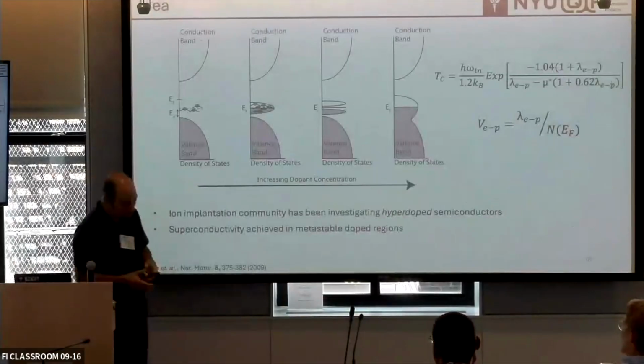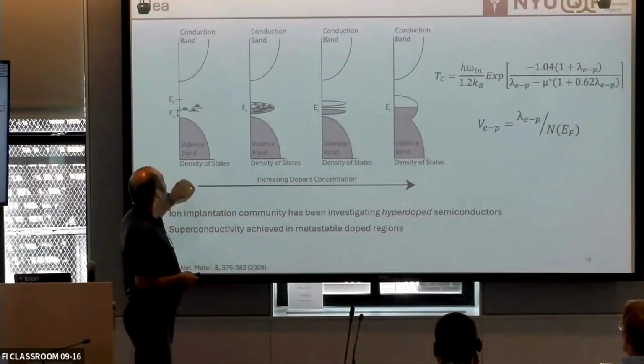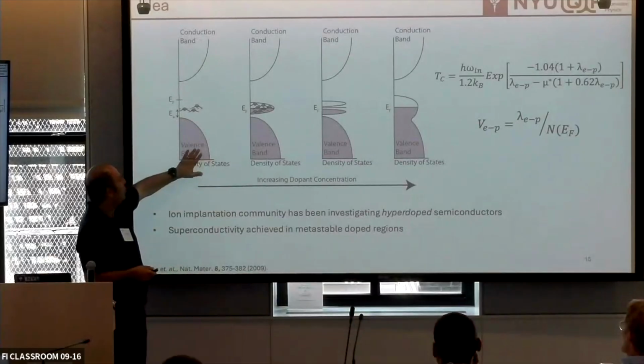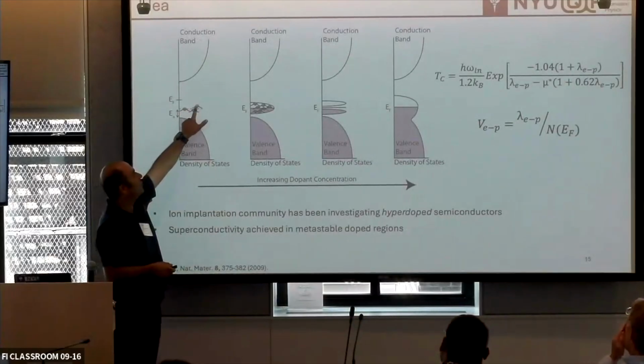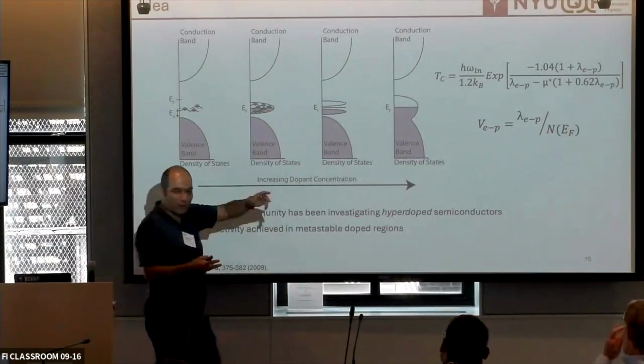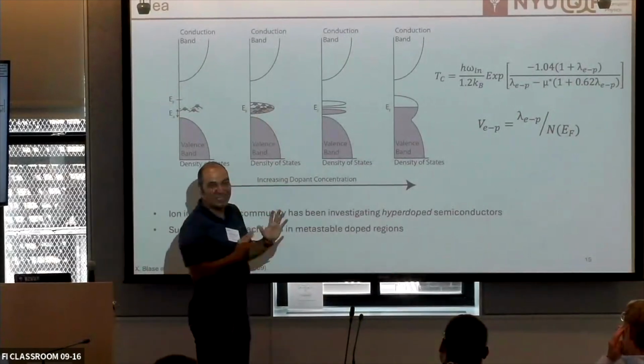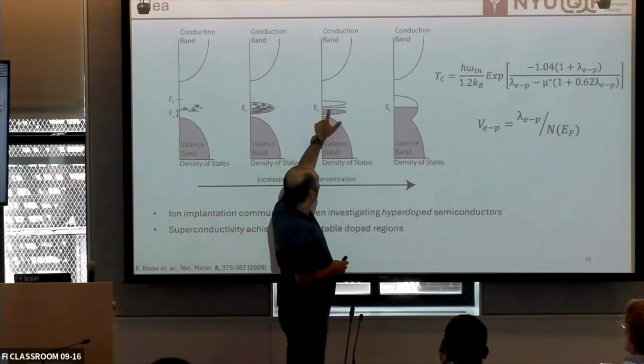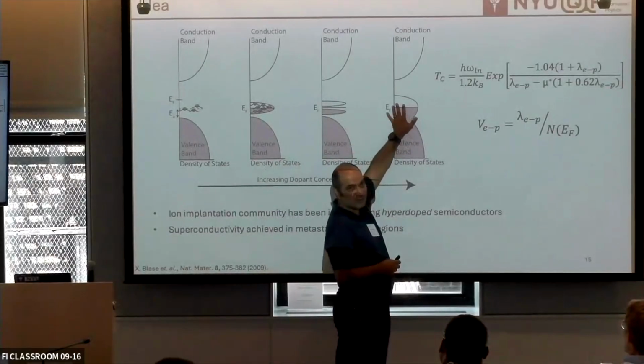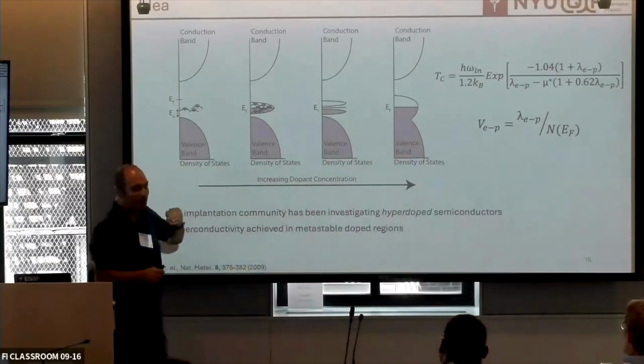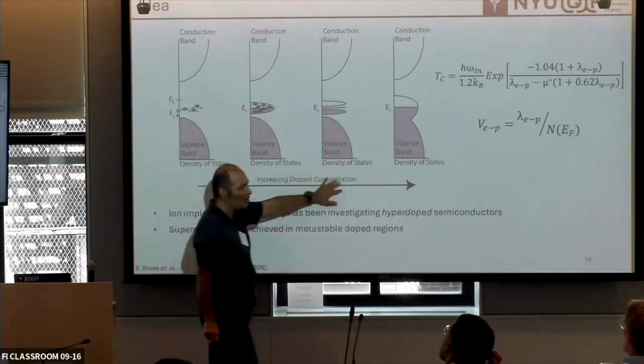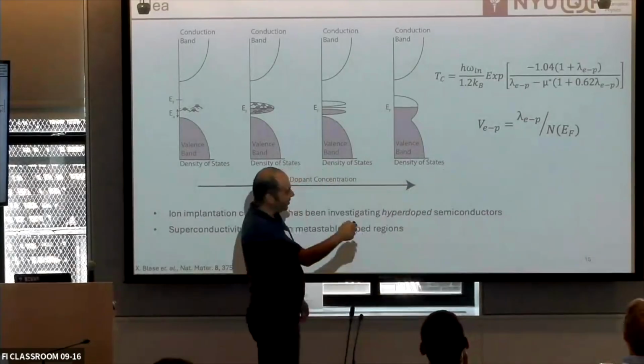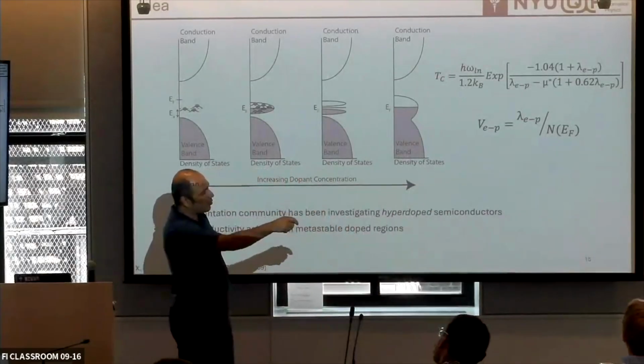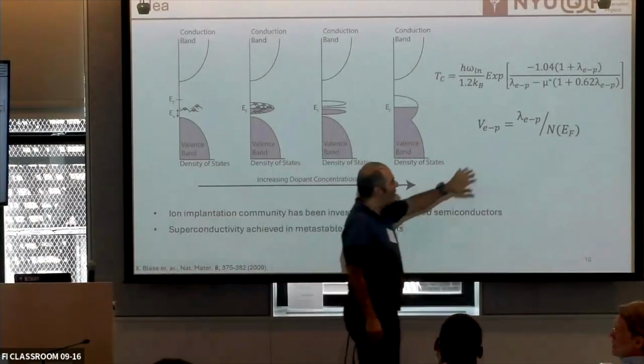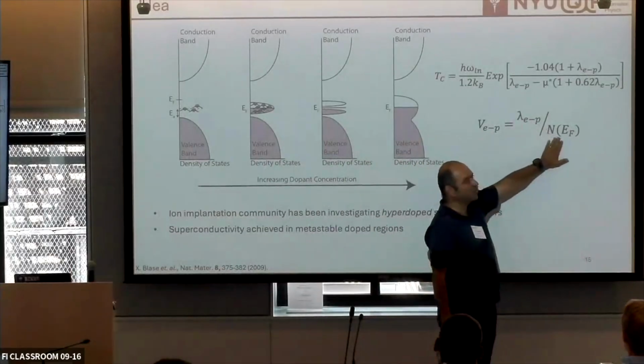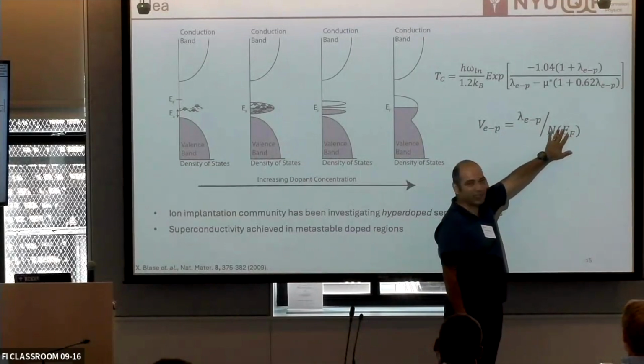The theory, which I should tell you up front, this is what was suggested, was that you basically start from a semiconductor, bare bone, valence band, conduction band. You put dopant, you have these localized states. You put more, you create a band. If this is clean enough and it's done right, you can open something like a Mott gap. And if you do more, then you get this superconductivity appearing at the highest doping. So we usually call this a hyperdoped semiconductor, right? And the BCS theory is very similar. It has the usual ingredients. What comes down at the end of the day is the electron-phonon coupling and the density of states. So if you have a flat band, this is where it gives you superconductivity.